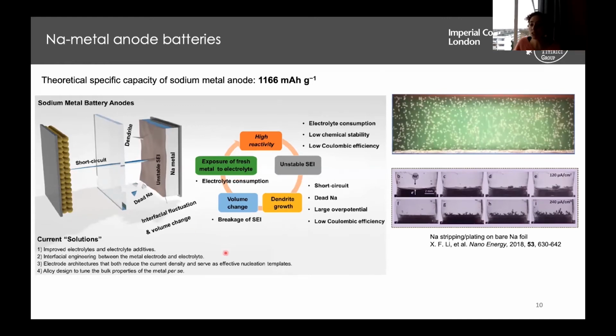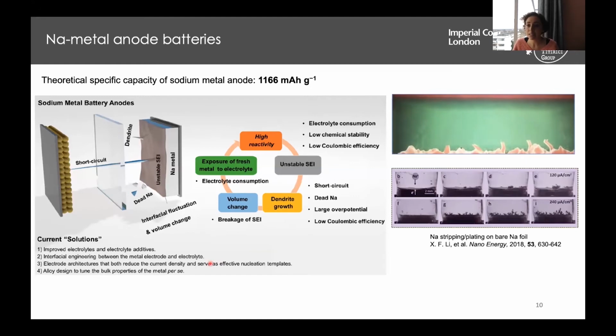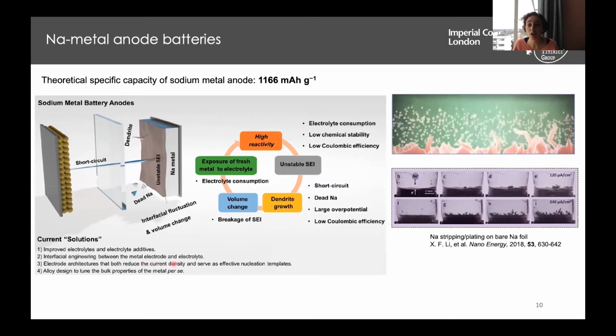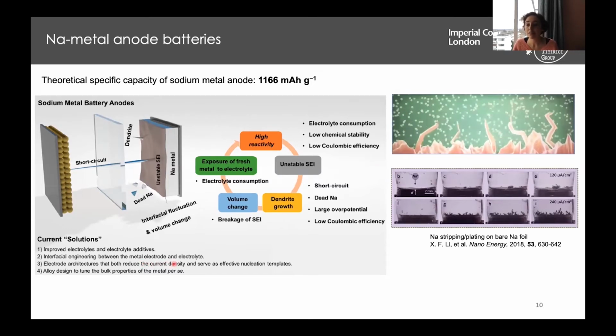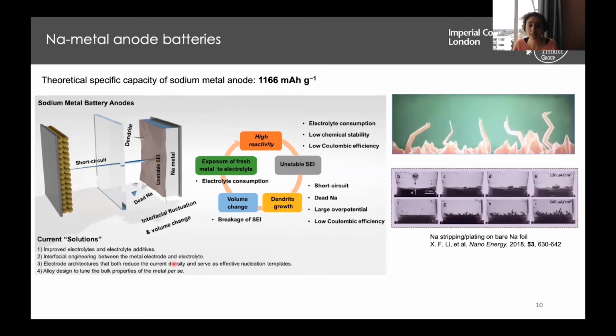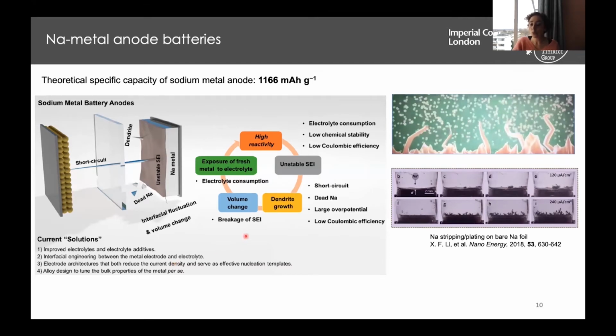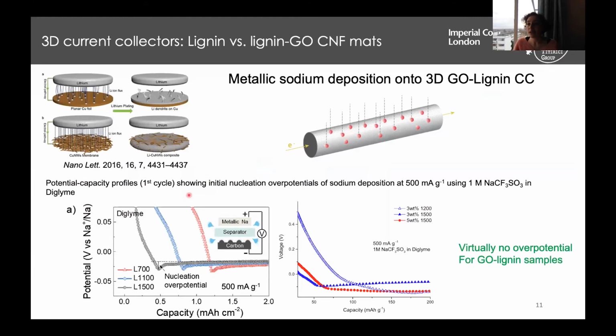So one of the strategies to inhibit this from happening is introducing the sodium into electrode architectures that can both reduce the current density, but at the same time serve as effective nucleation templates for the sodium metal. In a way, this has been done with other materials which are not as low cost and sustainable as the ones that we are proposing, but they will behave similarly to what we can see in this cartoon here.